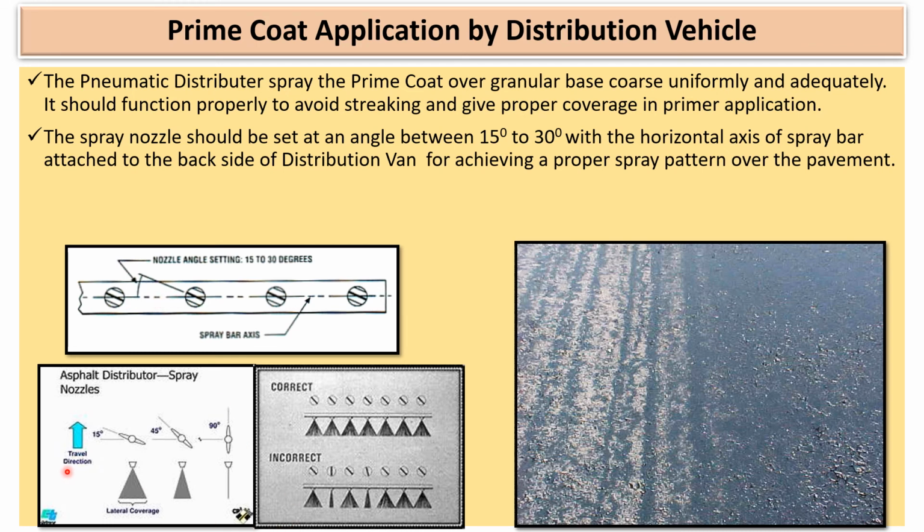In the photograph, you can see and compare the distribution width for various setting angle of the nozzle. Maximum lateral coverage with 15 degree of nozzle setting, and minimum width with 90 degree of the nozzle setting.